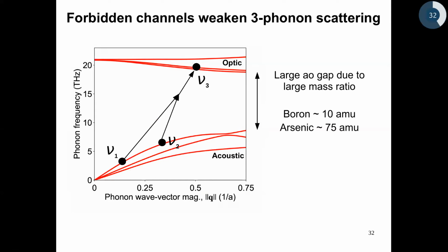Now let's think about a typical 3 phonon scattering process where you have 2 acoustic phonons scattering into an optic phonon. So any scattering process has to satisfy 2 constraints. The first one being the conservation of momentum or the wave vector. I have chosen these 3 points such that this equation is trivially satisfied. You can see that Q1 plus Q2 roughly adds up to Q3, which is the x-axis.